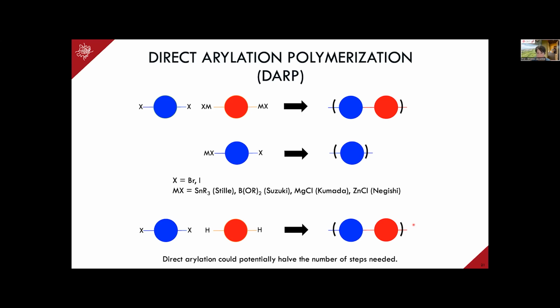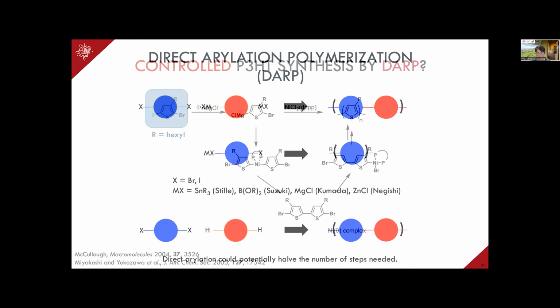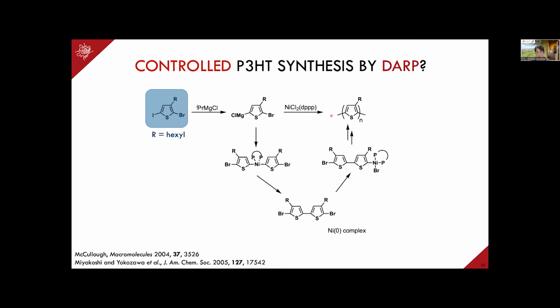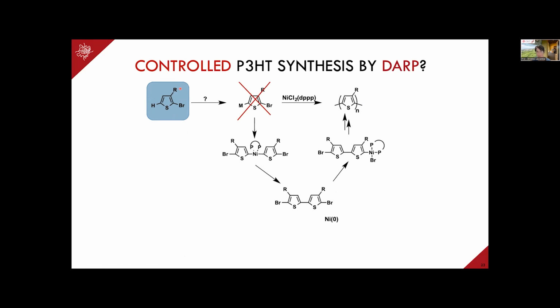For us, we were interested in DARP, but we were still interested in being able to do that controlled polymerization. So we wanted to do DARP, but still be able to control the molecular weight. In other words, we wanted to do that standard P3HT synthesis, but use DARP. Here I'm showing again the general way that we make P3HT. You start off with a bis-halogenated monomer. One side is activated with a Grignard, you add a catalyst and you get the polymer. But if we were to do DARP, it would be the following. We would start with a monohalogenated monomer, add a catalyst, and get the polymer.